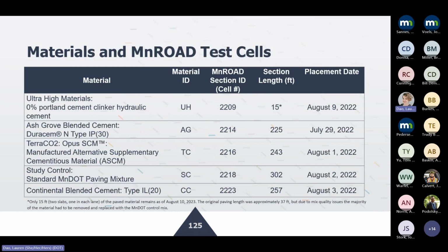All right, looking at the materials, we have 5 different test cells that we're monitoring as a part of this project. The first one is Ultra materials, and this one, the manufacturer said supposedly has 0% Portland cement clinker. AET did do an XRD testing to confirm that it does not have any Portland cement clinker, and we don't really know what the material is. We thought it could be a CSA type cement, but we are not sure.